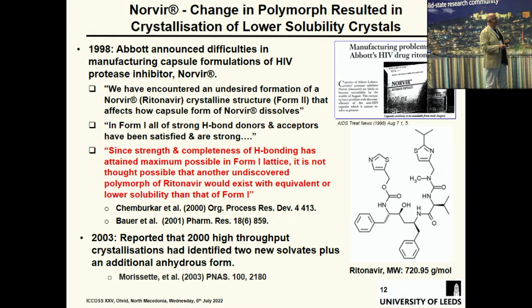We have encountered an undesirable formation of ritonavir crystalline form 2 that affects how they dissolve. In form 1, all the strong hydrogen bond donors and acceptors have been satisfied and are strong. Aha. So, question, is this true? And I think you see the answer is not quite. It's not quite true, and that is the problem. Since the strength and completeness of hydrogen bonding has been attained, the maximum possible in form 1, it is not thought possible that another undiscovered polymorph of ritonavir would exist with equivalent or lower solubility of form 1. Well, that proved to be the case.